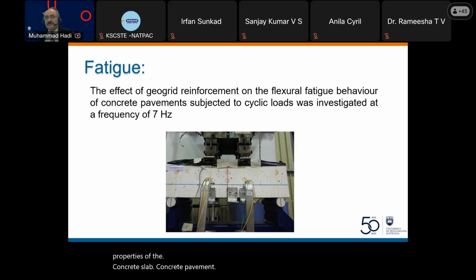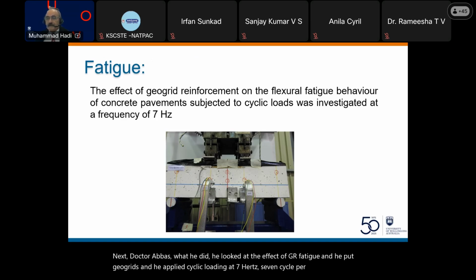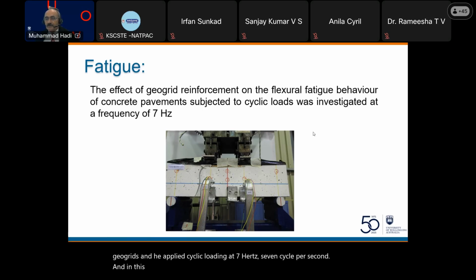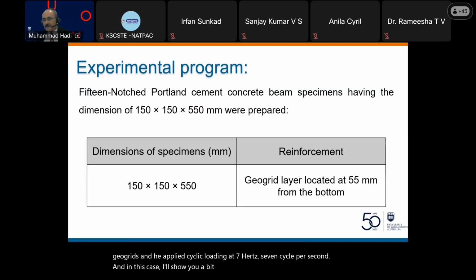Next, Dr. Abbas looked at the effect of fatigue, and he put geogrids and applied cyclic loading at 7 hertz, 7 cycles per second. In this case, I'll show you a bit more. Here we did beams, 150 by 150 cross section, 550 length, and we placed the geogrids at 55 millimeter from the bottom of the beam.